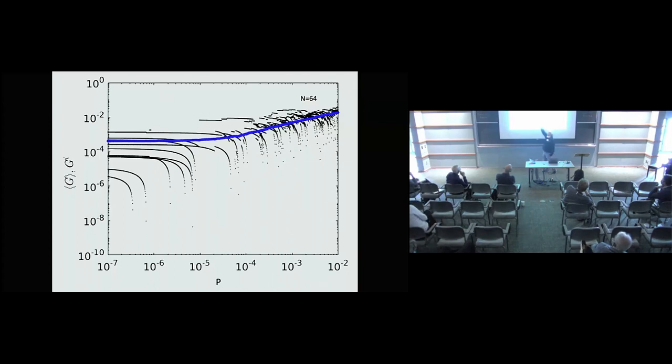So basically, it depends on where you are. Sometimes you can go down, sometimes you can go up. If you go isostatic to isostatic, there's a little bit of stochasticity. As you go to higher pressures, you'll increase the contact number, and then that will dominate the answer. And so in general, you'll go to higher shear modulus.